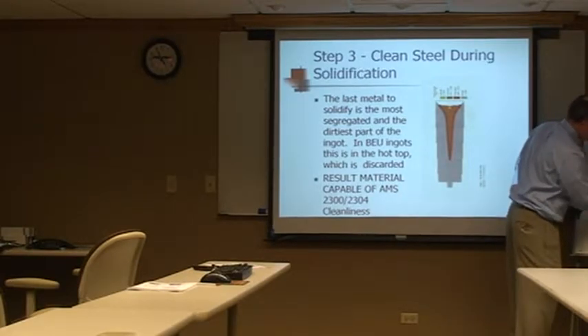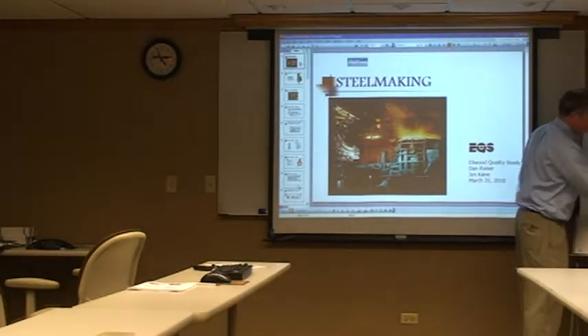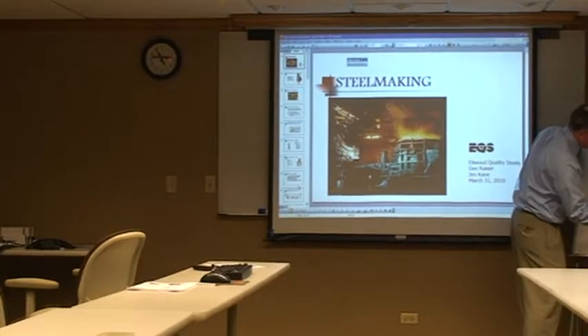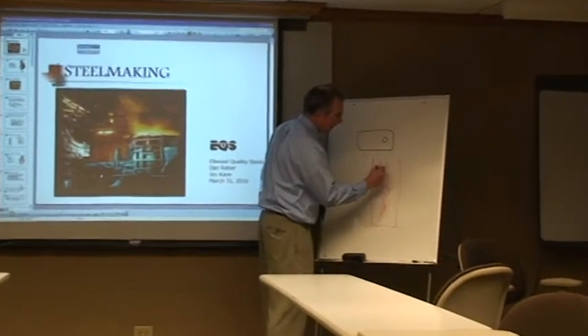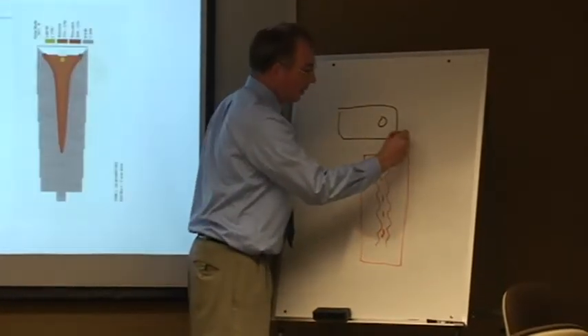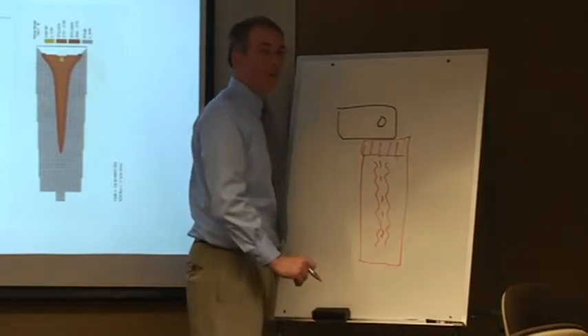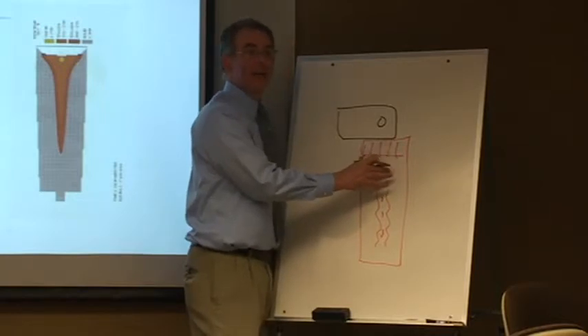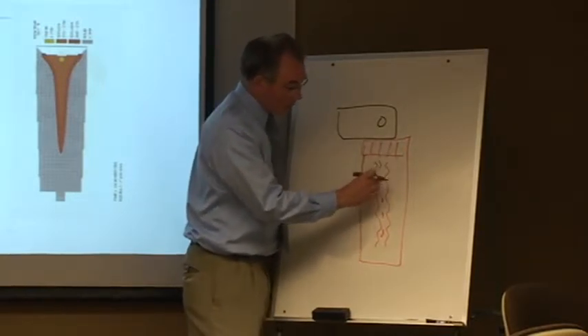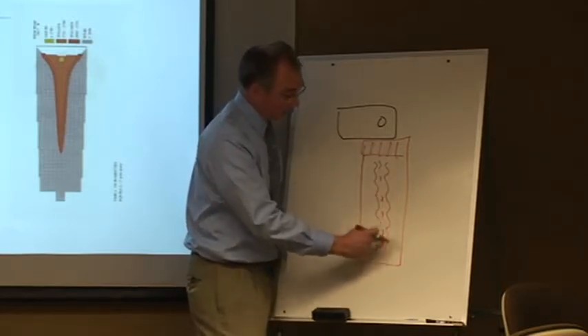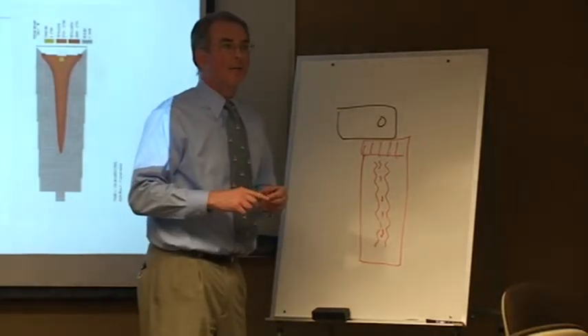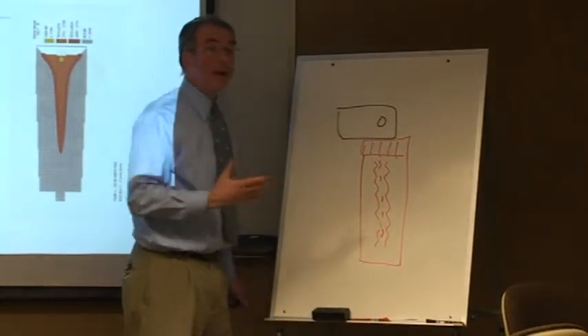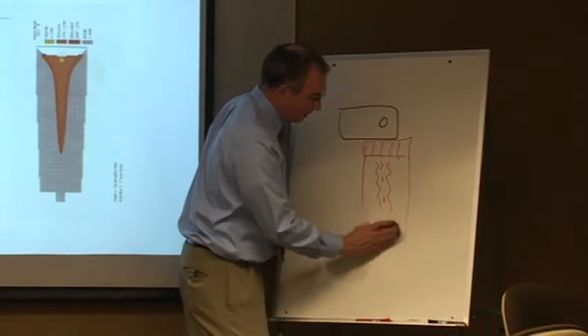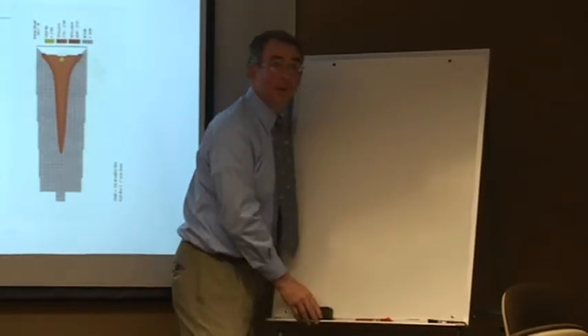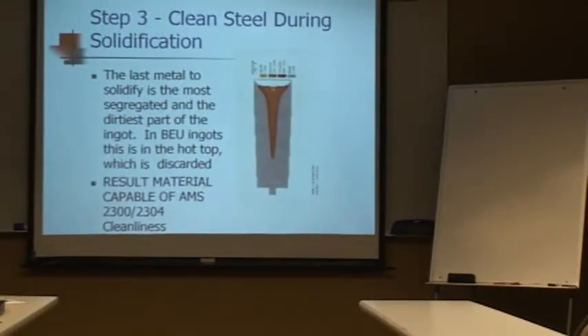Before we leave this, the thing I want to touch on here, that I don't have, is the cylindrical ingot. Why the difference? A cylindrical ingot is straight-sided, and the solidification front progresses this way, so you do end up with the last metal to solidify along the center line of the ingot. As a result, this hot top doesn't need to service the full ingot. It's really just worried about the top part, so you don't end up with a primary pipe. You do end up with a little bit, but it's broken up and strung out over the center line of the ingot, so you're not getting one specific area of concentration in the ingot body. Certainly the cylindrical ingots are the highest volume of ingots that we produce at EQS, with a 31-inch ingot. I think it's still the highest use grade ingot of those that we make at Scott Forge.